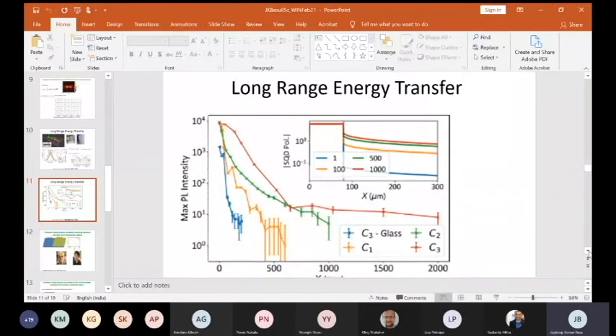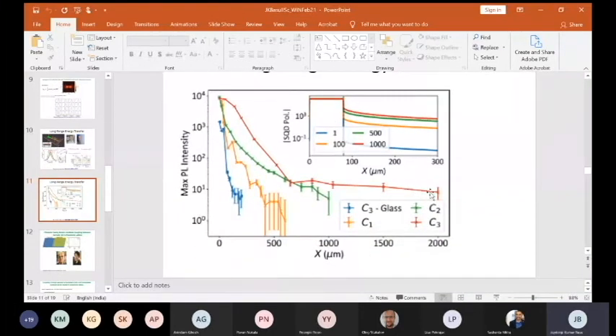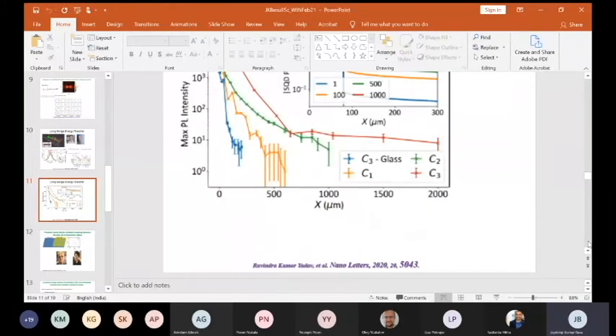If you look at the scale, this goes out almost up to 2 millimeters, and this one here is going almost up to one millimeter. So it's really very long range. You can actually see even the spectral signature almost up to about a millimeter. Beyond that, it becomes difficult to resolve because of very low intensity. So this is quite remarkable, two features. One we talked about is the collective emission mode that emerges. The second is very long-range emission that you see far away from the excitation region, which you would not expect to see if you only had the quantum dot. Clearly, the exciton polaritons which are generated allow energy to be transferred over such large distances.